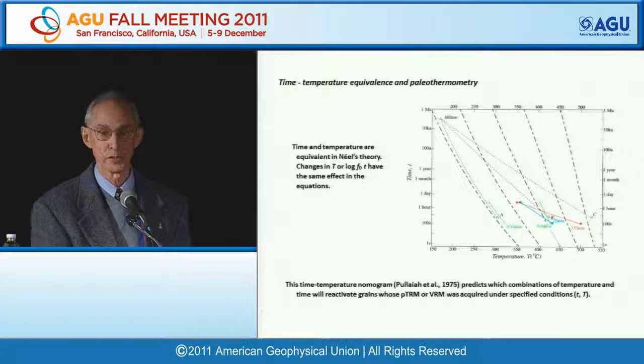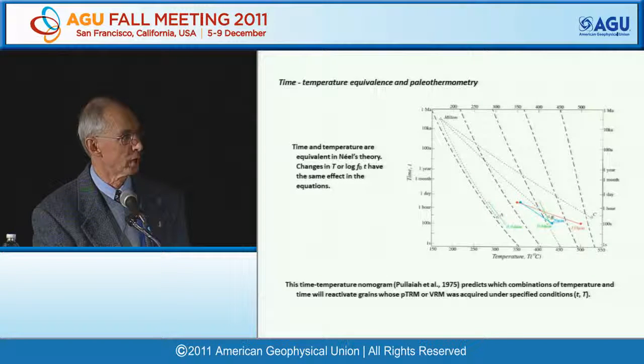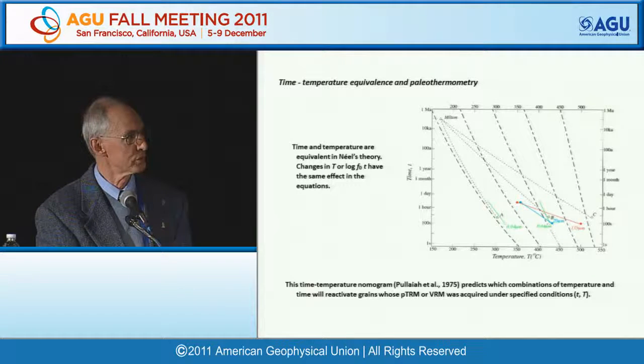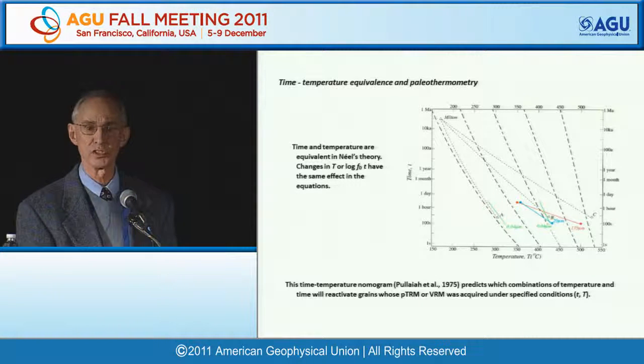predicts. So if you stick to single domain grains, here's another example with green data, or over a much longer term, the Milton monzonite of Australia, magnetized on a 100,000-year time scale, demagnetized in 10-minute experiments at considerably higher temperatures. Everything is beautiful. It follows these curves.